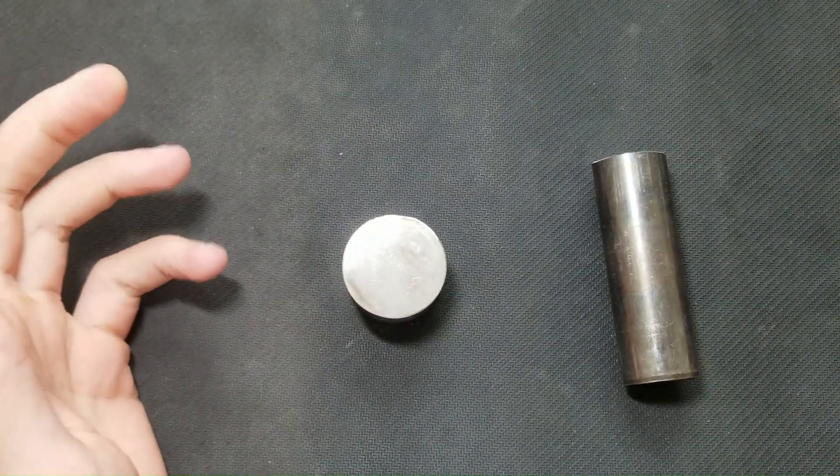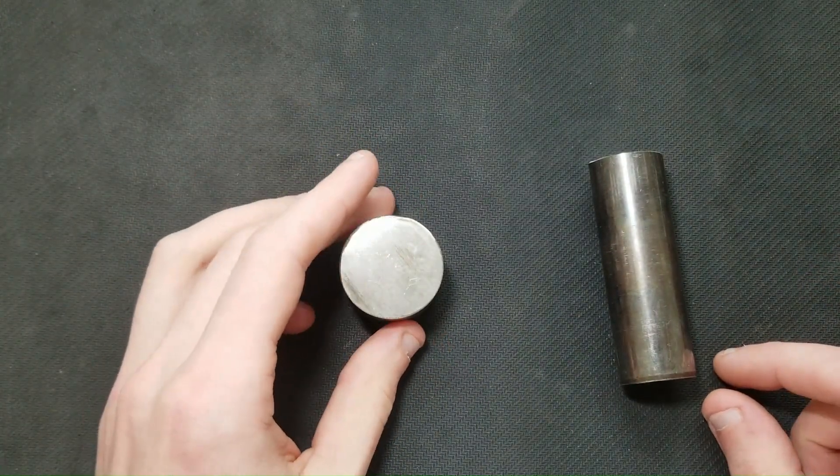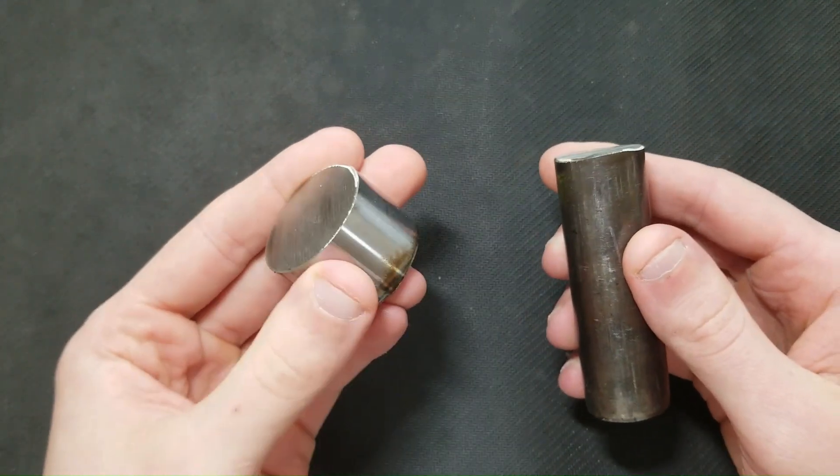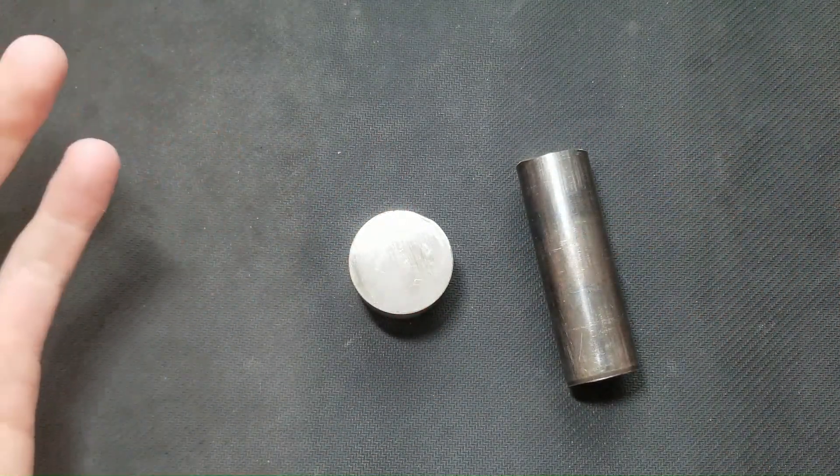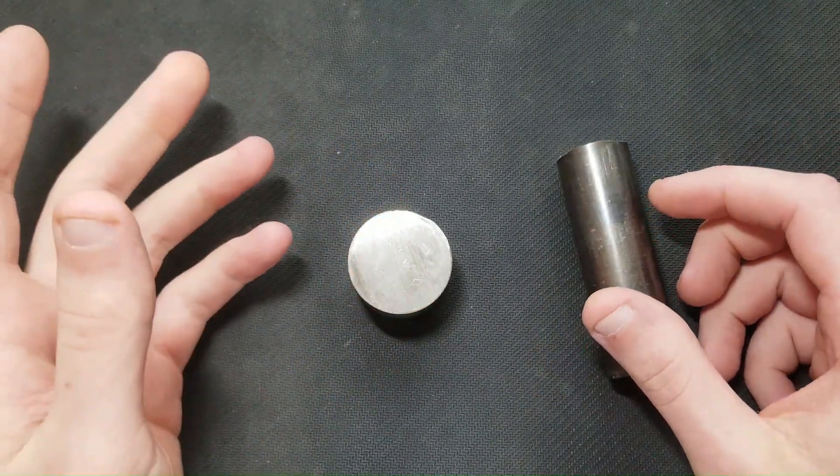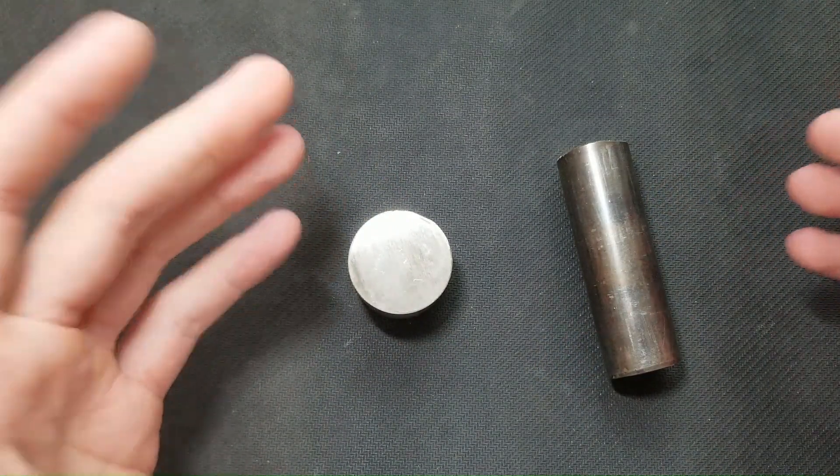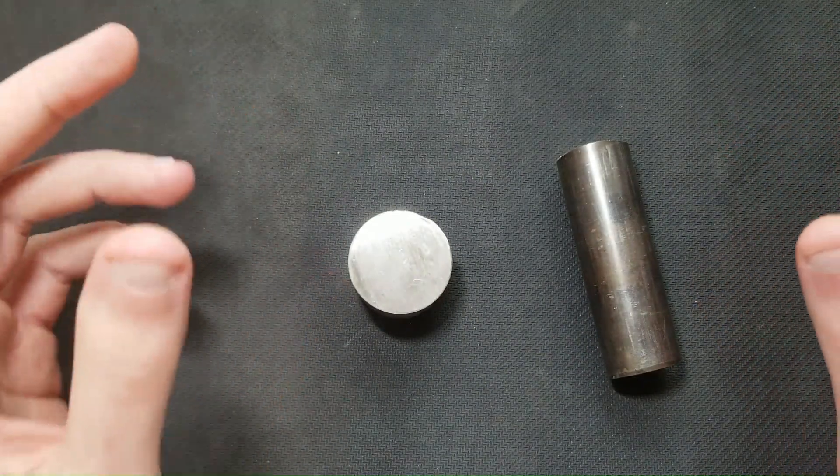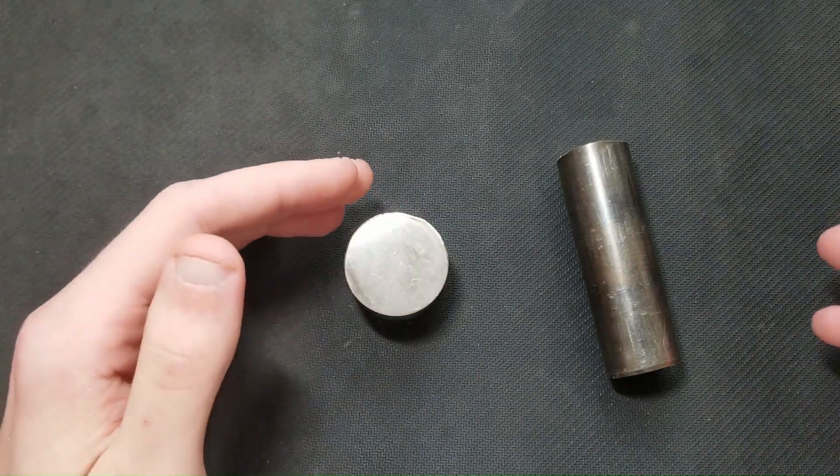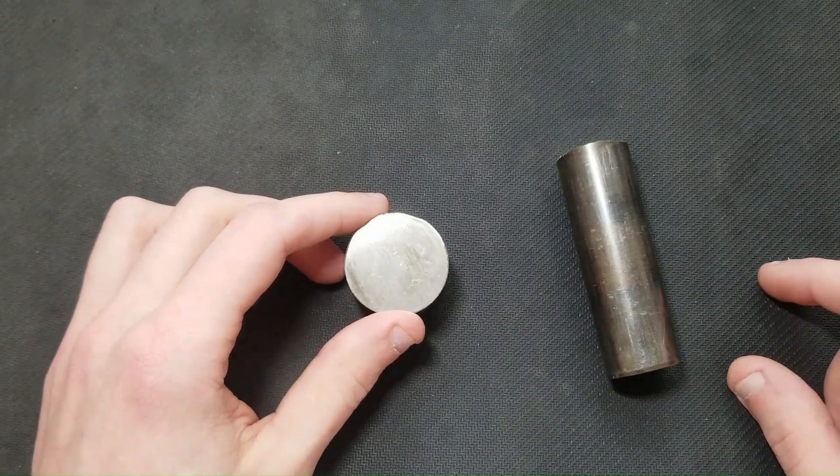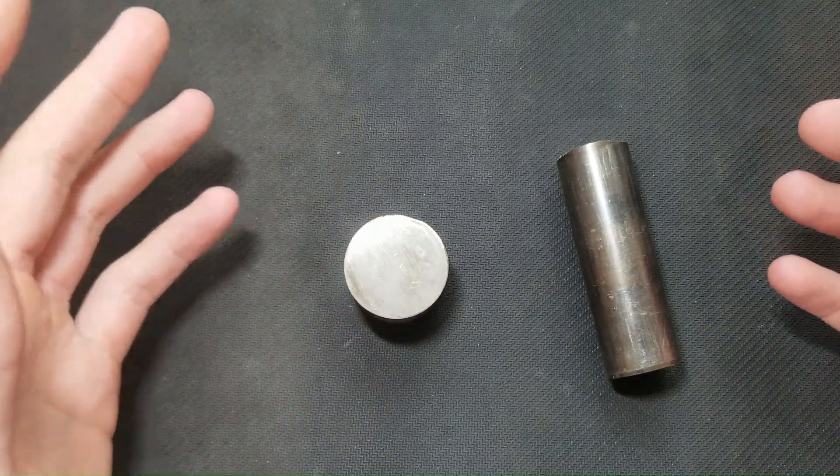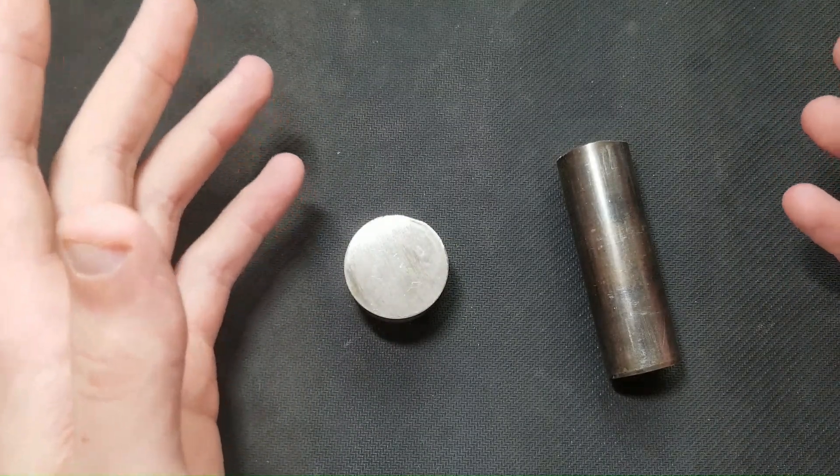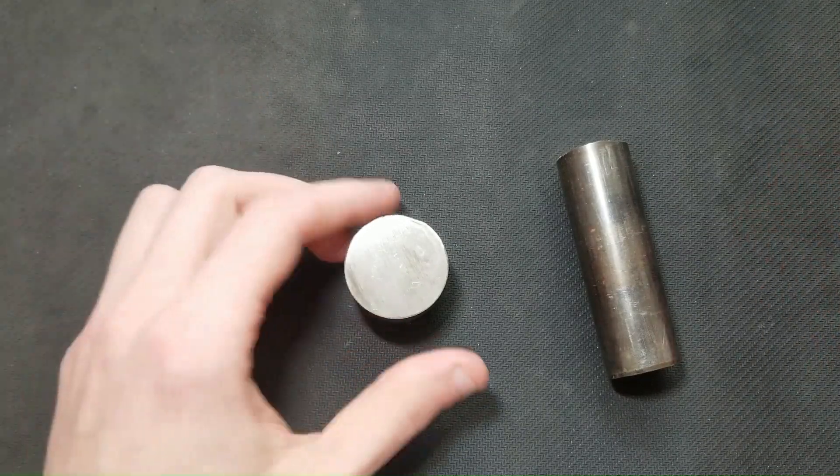The last one I will be discussing and testing is 17-4 precipitation hardened stainless steel. This is some super tough stuff. I chose this because high-end pistol slides will be machined out of this. 17-4 is kind of like a weird mix of 300 and 400 series. It's harder and more wear resistant and can be heat treated like the 400 series. It has a martensitic crystal structure like the 400 series but it contains nickel like the 300 series. It has around 15 to 17.5 percent chromium. It has good mechanical properties at elevated temperatures and good corrosion resistance like the 300 series but it will generally be easier to machine. It also is going to be one of the easiest to weld of all the stainless steels.